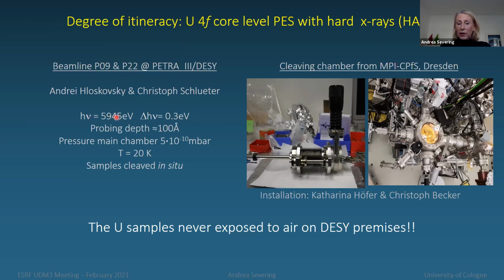We came in with 6 keV incident energy, but nevertheless, photoelectron spectroscopy is a surface technique, even when you use hard X-rays, so we have to cleave the samples, which is often a problem, but we were lucky that radio protection at DESY allowed us to cleave these uranium samples, but the demand was that they never should be exposed to air on the DESY premises. And this we can do by coming with our samples in a load lock. This has been designed at the Max Planck; we are bringing a cleaving chamber that is mounted to the end station before the experiment, and it's dismounted after the experiment, so that we fulfill the radio protection demand and we are not leaving behind any cleaved crumbs of uranium. So even though DESY is an open site, we are allowed to cleave uranium samples.